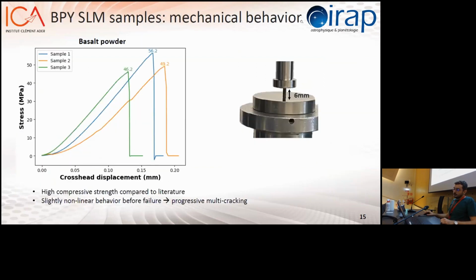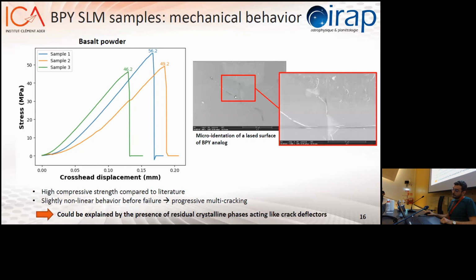Now I will show you some aspects of the mechanical behavior, because we have conducted some compression strength tests. The obvious thing here is the maximum stress we can apply to our cylinders. We have quite promising values, with a compressive strength of 56 megapascal at max. The reason for those values is that you can see at the end of the curves it is slightly non-linear before the failure. That is a sign of progressive multi-cracking in the material. That can be explained because at the end of the process, we still have some crystalline inclusions in the material that act like crack deflectors. So it is a good thing to still have some residual crystalline phase in the material that can deflect those cracks.